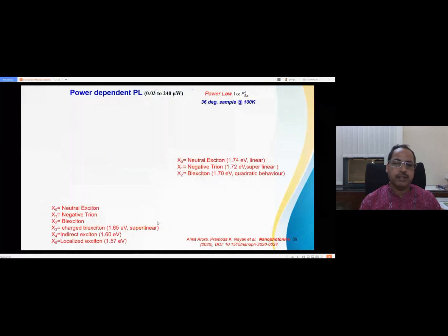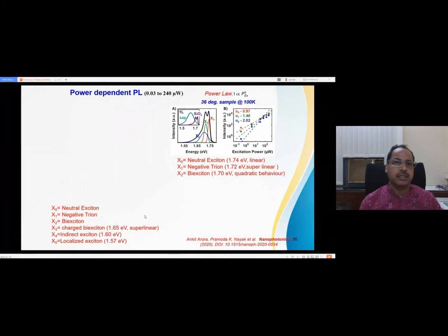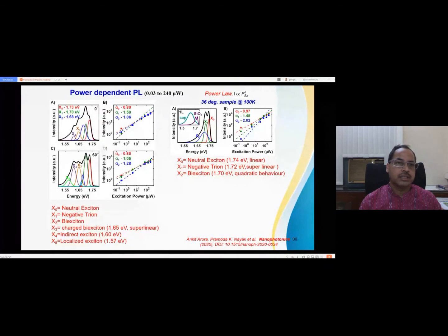And next we deconvolute this peak, and here we can see that when you deconvolute this PL peak, so many features are coming. X0 is a neutral exciton. This is the negative trion. This is the bi-exciton. Then we got the charged bi-exciton, indirect exciton, localized exciton.